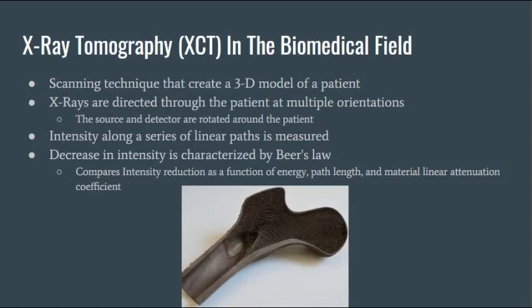Right now, implants are pretty standardized and they don't tailor to different morphology. So the wrong type of implant could cause fractures in the femur later in life. By taking this 3D model and then printing it, usually out of a titanium alloy, and customizing this print to the individual, it allows for a safer implant with fewer fractures down the road. And this would not be possible without the CT technology, which allows doctors to get that perfect image of the human.